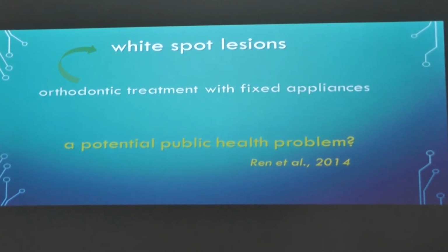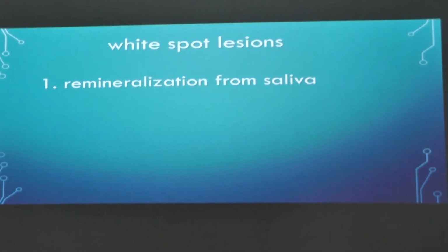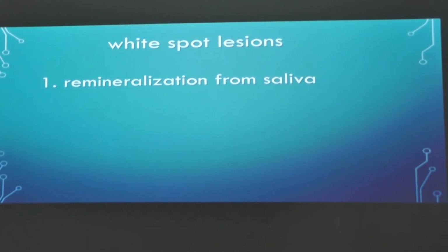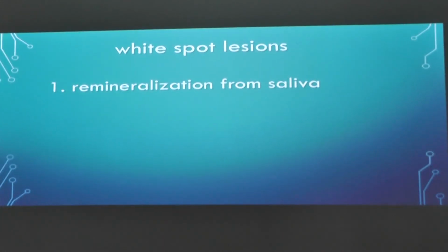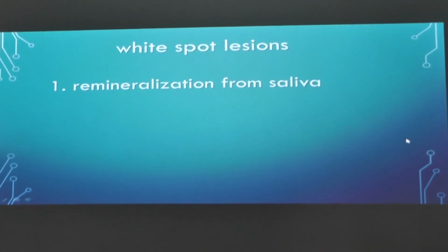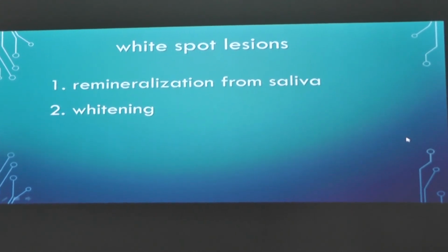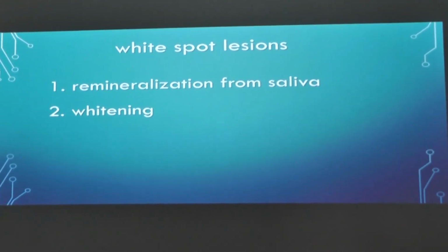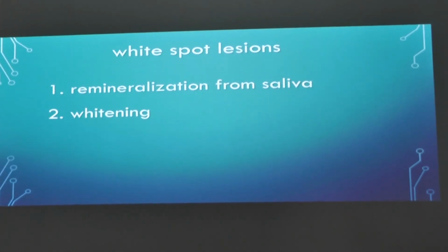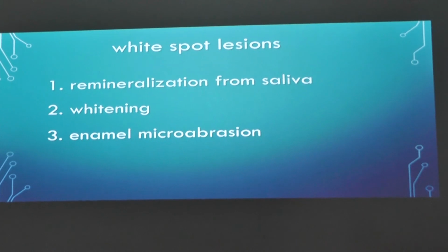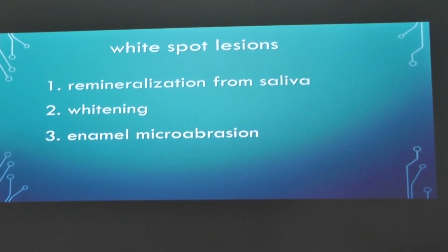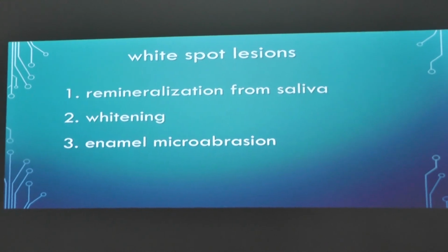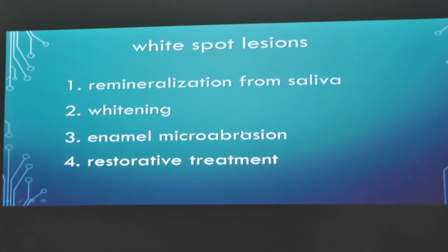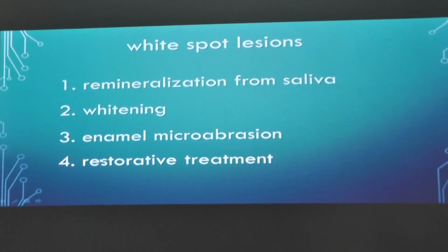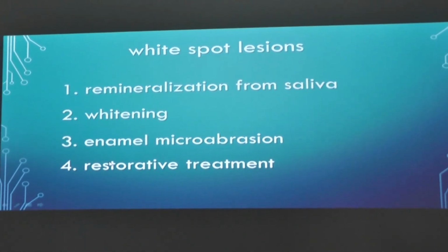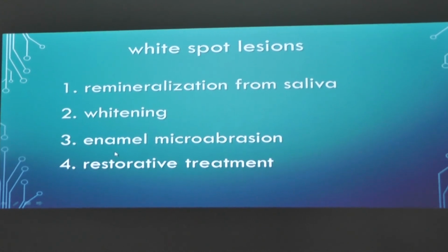So how do we treat them? The first suggestion is just to let it remineralize from saliva after debonding for a certain period of a couple of months, maybe until the next retention control. Then we can do tooth whitening, so that the remaining enamel is not yellow, so that the contrast is not seen as much. And again, microabrasion could be useful also in these cases in combination with whitening. These are all non-invasive treatments. And finally, we can also perform restorative treatment, which is invasive and also more expensive.